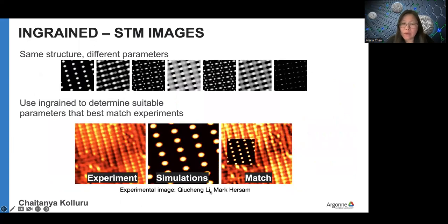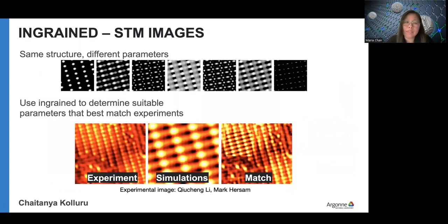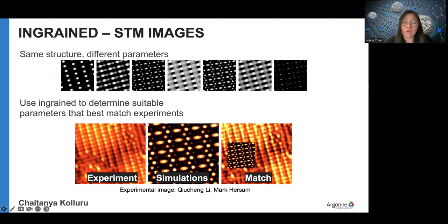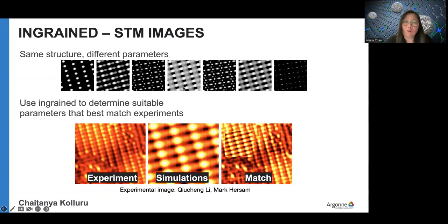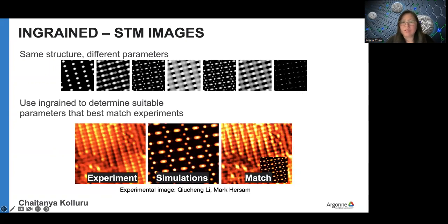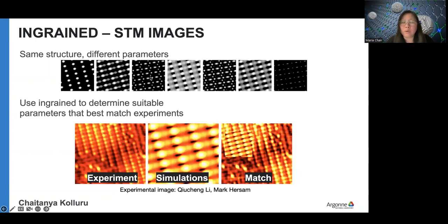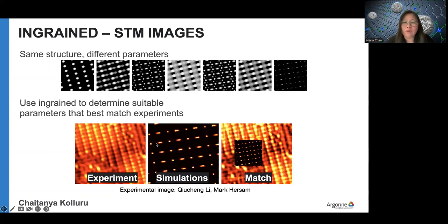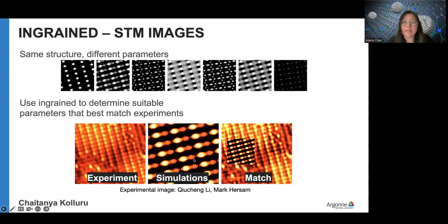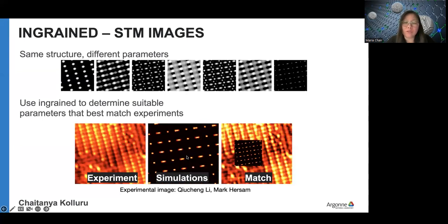We extended that to scanning tunneling microscopy, STM, where there's an additional problem because even when you have the same structure, so this is a surface now and not an interface, STM probes not the atom directly, but the electron density isosurfaces, essentially, or tunneling probability, really, the potential. There's a lot of different images that you can get for the same surface if you apply different parameters in the simulations. So Ingrain additionally added optimization for the simulation parameters.